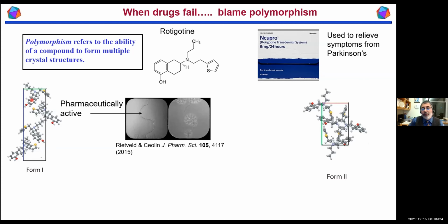And often the way that this happens, if it's not spontaneous, is you have a little seed of a contaminant, which in this case is the wrong crystal structure, getting into your manufacturing process somewhere, and these seeds get into the crystalline form, and it causes a conversion that may happen on a very slow time scale. Well, it turns out that these new crystals that are forming on the patches are very stable, and so they're no longer absorbed by the skin, and so this becomes pharmaceutically inactive. In other words, the drug fails.